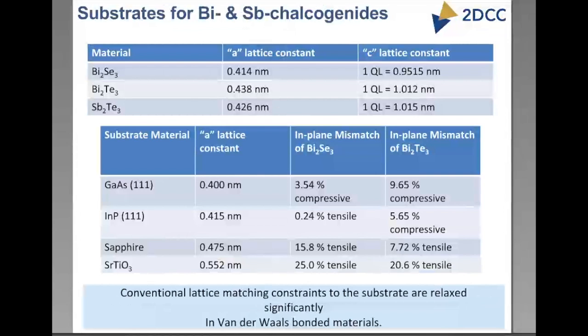One of the considerations, of course, in doing molecular beam epitaxy or epitaxial growth of any kind, conventionally, the idea has been that you want to make sure that you choose a substrate which is lattice matched to whatever you're trying to grow on top. And so from that viewpoint, we've summarized over here the lattice constants of these common topological insulators that we're interested in, and some common substrates that we are interested in growing on, and other people have certainly used. We have used these substrates. And the conventional wisdom, of course, in the business of MBE or any kind of epitaxial growth, MOCVD and so on, is that you want to have a good lattice match with the substrate.